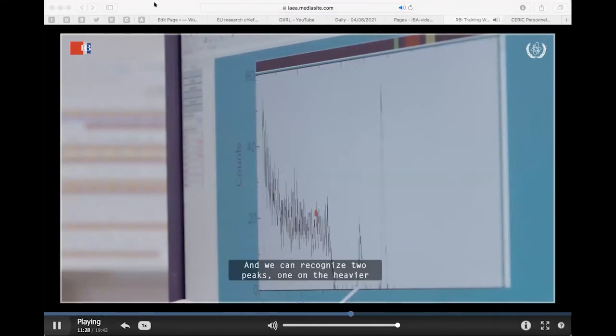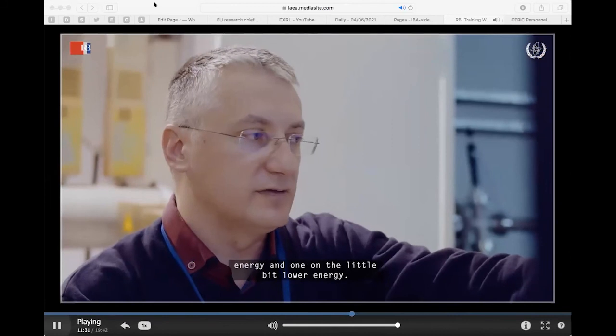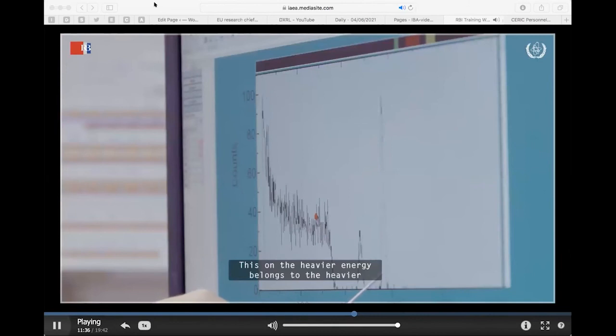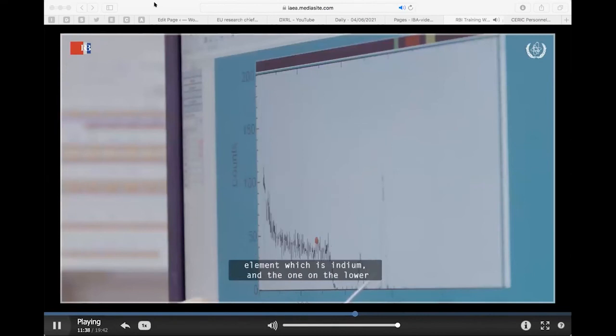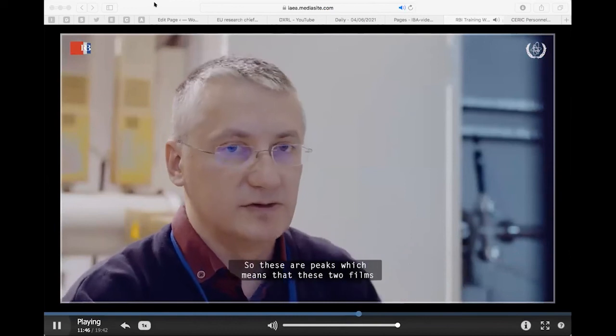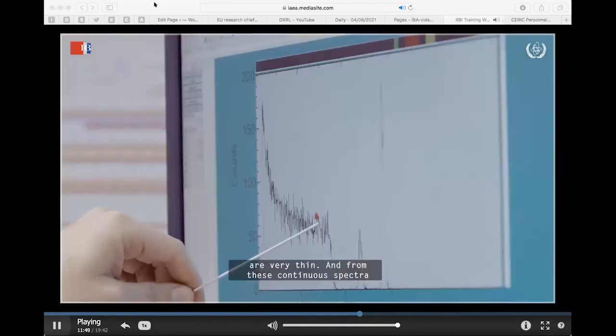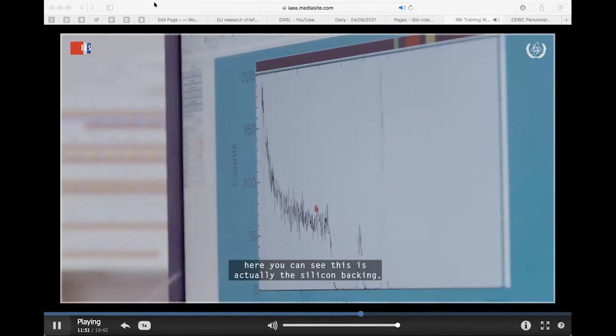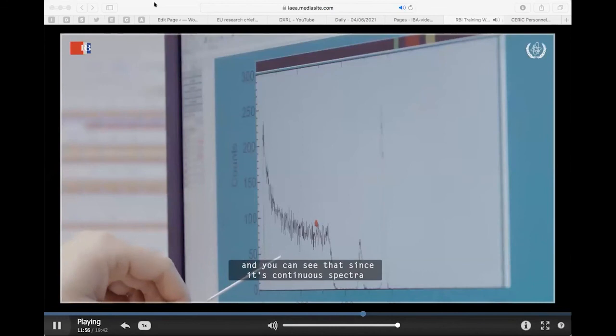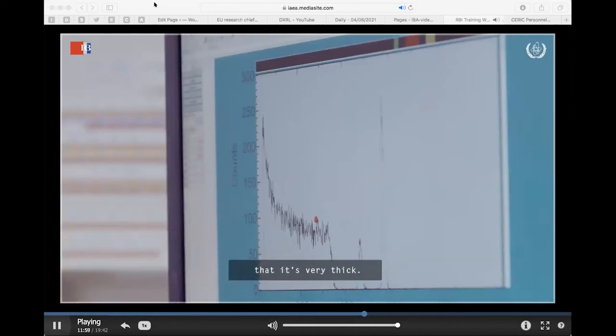So you can immediately see this spectra here on the monitor. And we can recognize two peaks, one on the higher energy, one on a little bit lower energy. This on the higher energy belongs to the heavier element, which is indium. And this on the lower energy corresponds to the chromium. So these are peaks, which means that these two films are very thin. And from this continuous spectra here, you can see this is actually the silicon backing, and since it's continuous spectra, it's very thick.